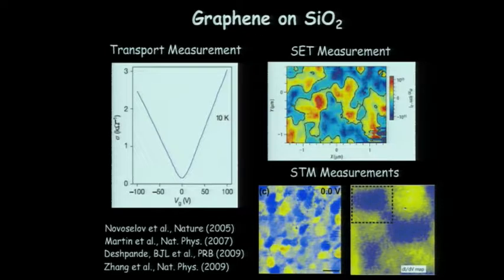And that's because, well, first, the oxide is relatively thick, but also there's quite a bit of disorder in these samples. So there's a lot of disorder in the graphene that's coming from the substrate. This is work from the Jacobi group looking at the fluctuation in the silicon oxide. So the charge density fluctuations there under these devices, and you can see it's on the order of 10 to the 11 electrons per square centimeter. So this graphene monolayer that you have sitting on there has these fluctuations of like 10 to the 11 per square centimeter in the density in it.